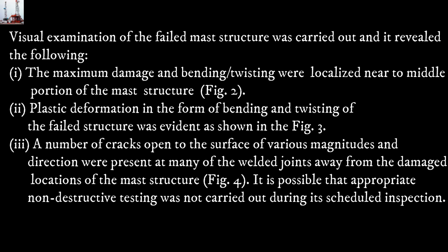Fig. 3. III. A number of cracks open to the surface, of various magnitudes and directions, were present at many of the welded joints away from the damaged locations of the mast structure, Fig. 4. It is possible that appropriate non-destructive testing was not carried out during its scheduled inspection.